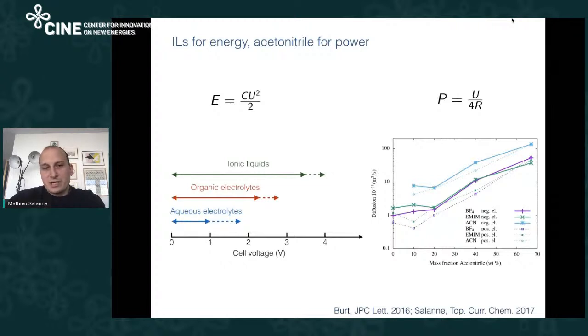systems. So in the end, the capacitance is the same in all these types of electrolyte, or almost the same. And what is changing is the operating voltage and the resistance. And so in the end, it means that ionic liquids are good when you want large energy density, but acetonitrile is much better when you want large power density. And then it's up to you depending on the application you target.